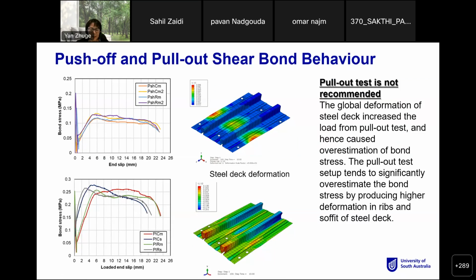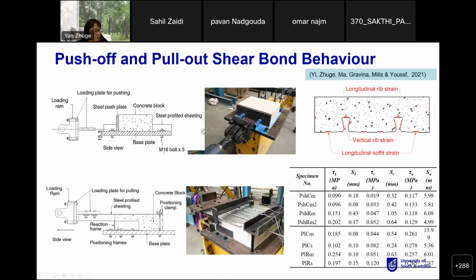So we found out, as I said, the maximum bond stress from each test is quite different between push off and pull out. So that's why we performed some finite element analysis as well to further investigate the reason. So that is the finite element model for the steel deck deformation, and that is the load deflection curve. So both push off and pull out tests are compared with the finite element model. So from this, we find out the pull out results, which is this curve, you can see they're not really fully consistent with the push off test.